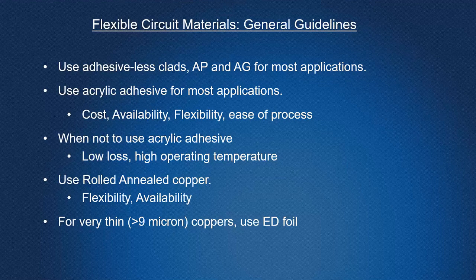Chris, I'm sorry, what's a good maximum temperature for these acrylic adhesives, do you think? So its rated operating temperature is 105 Celsius. I've known people to use it up to 125 in continuous operating conditions, not a problem. Its decomp is 315 Celsius. So the decomp is pretty high. What happens with the acrylic adhesive is it will soften at the higher temperatures, but as soon as it's cooled, it goes down to its normal condition.